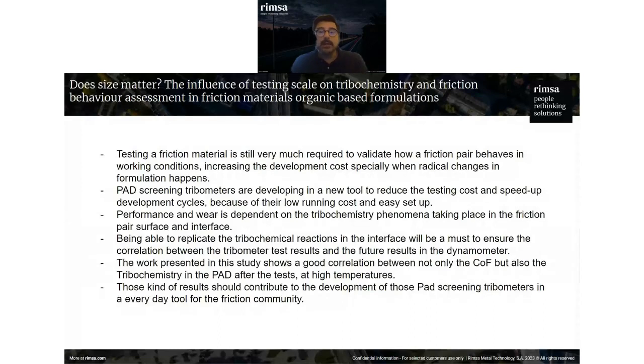So performance and wear are dependent, of course, on the tribochemistry phenomena taking place on the friction pair surface and interface. So you have seen that we have this transfer film, and we need to generate these reactions to make sure that the engineering results we are getting from this test can be correlated between a tribometer and a dynamometer. So being able to replicate these tribochemical reactions in the interface is a must to ensure the correlation.